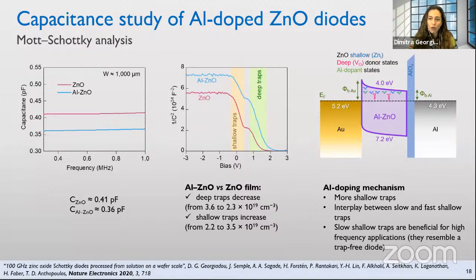The Mott-Schottky analysis on the capacitance-voltage data revealed the presence of both deep and shallow trap states, as you can see here. However, from the analysis, we found out that in the aluminum-doped zinc oxide film, the concentration of deep traps decreases and that of shallow traps increases. A mechanism we proposed for this is that the aluminum oxide anions that may be formed due to the presence of aluminum would fill some of the deep traps, while the aluminum cations may be substituting the zinc cations, providing extra electrons at shallow donor levels. And these attributes are expected to affect the high frequency operation of our diodes. Let's see if this is actually true.